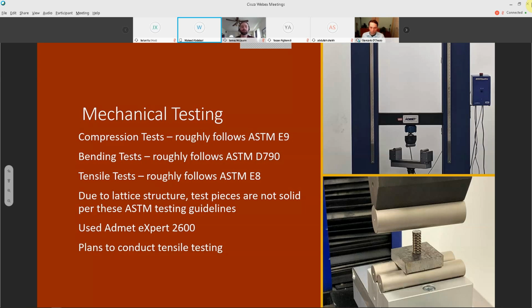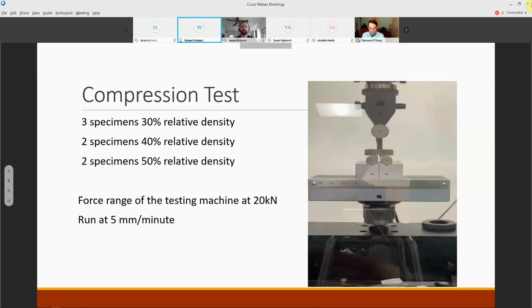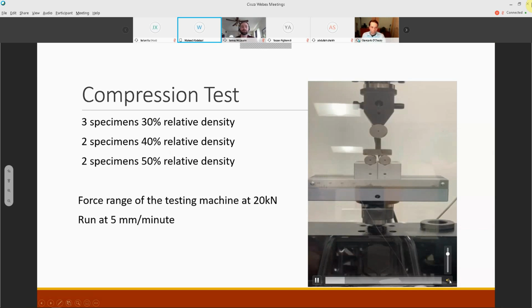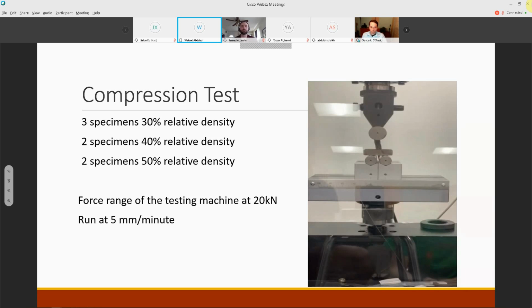We had plans to conduct the tensile testing, but due to the spring pandemic, the work for it was paused. So the next slide here is the compression test in a video. We had seven specimens in total for our compression: 3 in 30%, 2 in 40%, and 2 in 50%. The test speed was run at 5 millimeters per minute, and the force range was set to 20 kilonewtons.